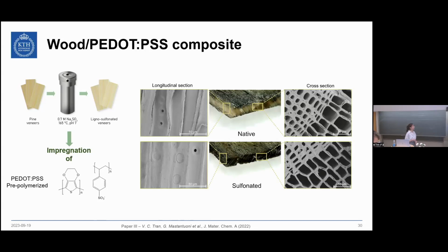And we could see the influence of the sulfonation already macroscopically, because if we try to introduce the polymer, which is black in color, into native wood, then we can see that we could not have any polymer within the material. And this is actually a very thin material. It's only 0.75 millimeters. Instead, if we use sulfonated wood, then we could see how the polymer could go through the material without problems. Similarly, from SEM, we could not see any presence of the polymer in the case of native wood, but we could actually spot the polymer as a very thin layer on top of the lumen surface in the case of the sulfonated wood.